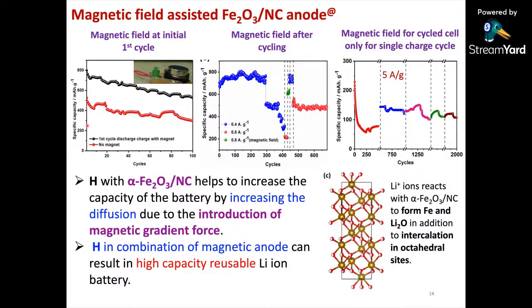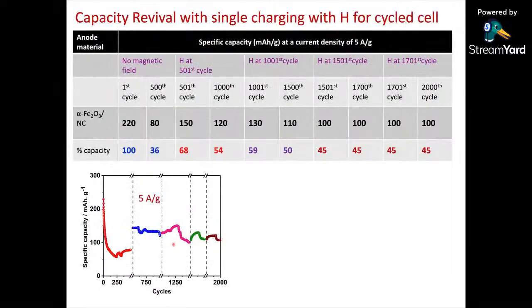So what we have done is that we have gone to a high current density of 5 ampere per gram. You can see this is the number of cycles and capacity. Very close to 500 cycles, it has gone below 100 milliampere hour per gram, very close to 80 milliampere hour per gram. Now we applied the magnetic field. 500 we have done, and then 1000, 1250, 1500, and 2000. And I'll show you the exact same figure with the values.